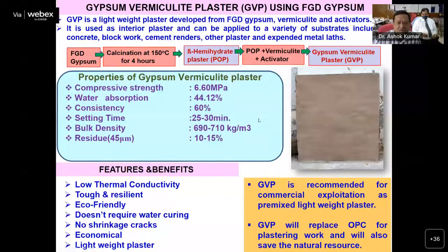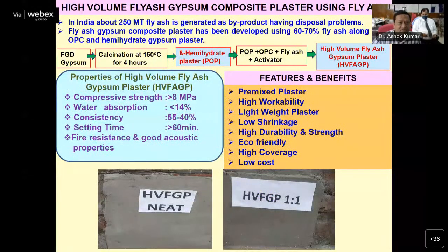The next plaster which we have developed is high volume fly ash composite plaster. As we know, in India about 250 million tons of fly ash is generated as a byproduct from thermal power plants, which has disposal problems. So in this work we have developed this high volume fly ash plaster, and about 60 to 70% fly ash is utilized for development of this plaster using POP and OPC cement. Activators were also blended with these materials.